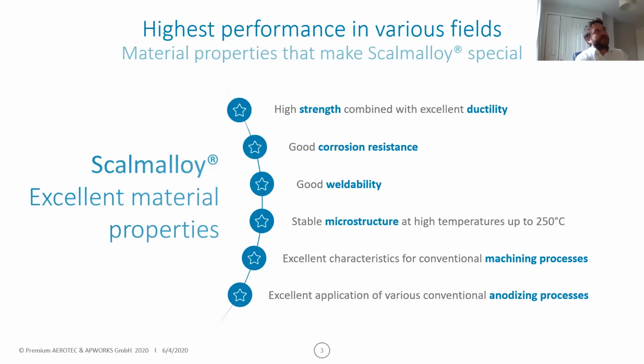And often, while the elongation or ductility is quite good in the primary direction, if you go into the short transverse direction, often they have very low ductility, so quite brittle behavior. And this can be quite challenging, not just from a static design point of view, but actually when you start to get into things like corrosion behavior because of grain boundaries, and fatigue, and the relationship between corrosion and fatigue.